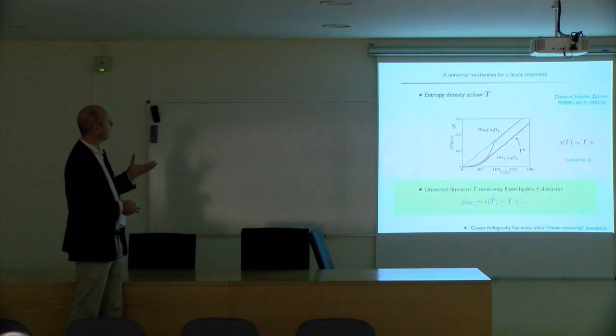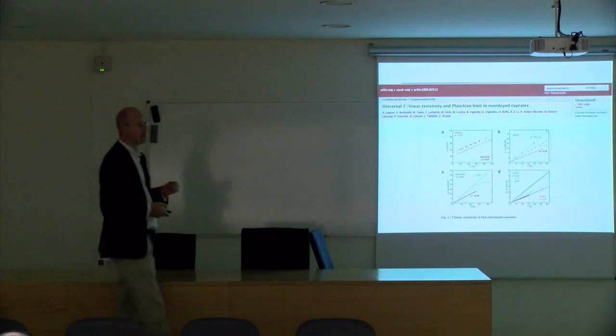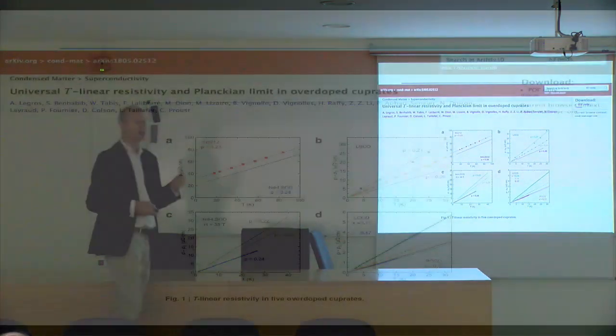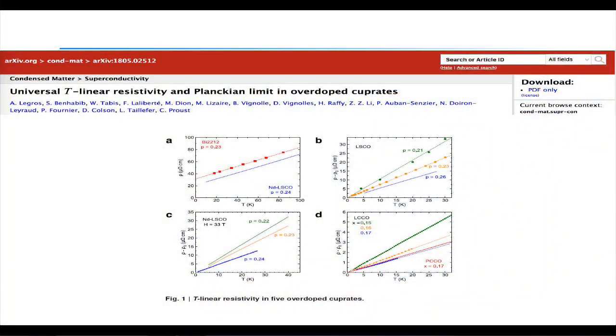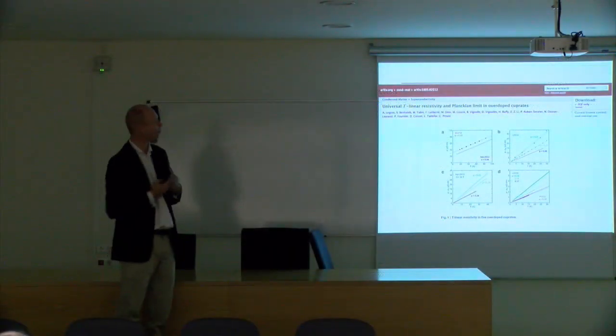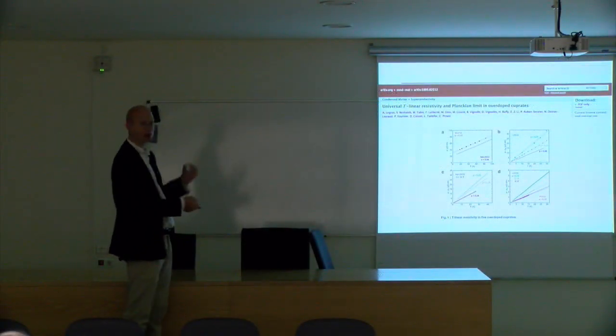But an even more interesting result is the following. Remember that the entropy density scale is T, but if you look more precisely first at the resistivity, here you see the resistivity as a function of T. It behaves beautifully as a straight line. However, the slope, if you're very careful, changes slightly with doping.